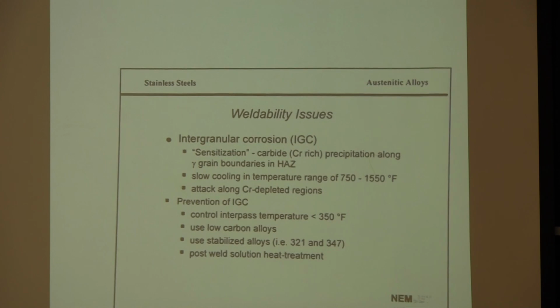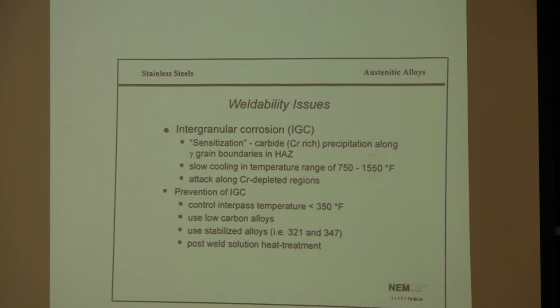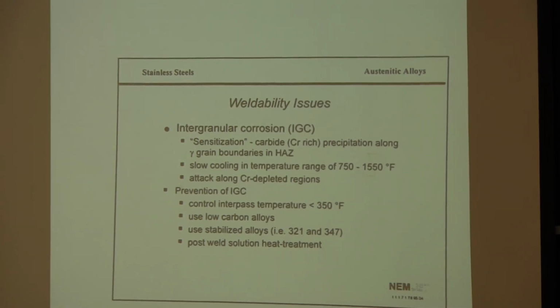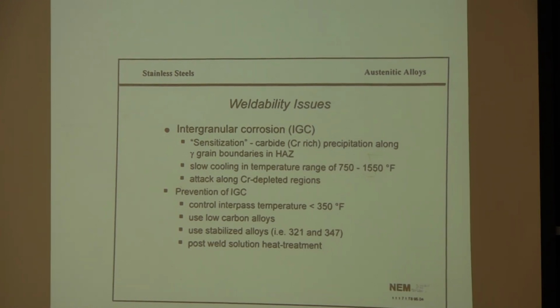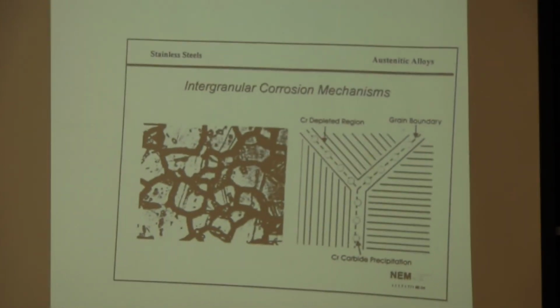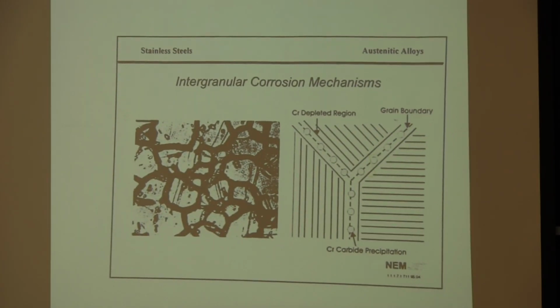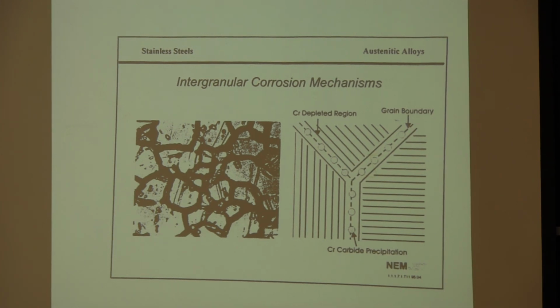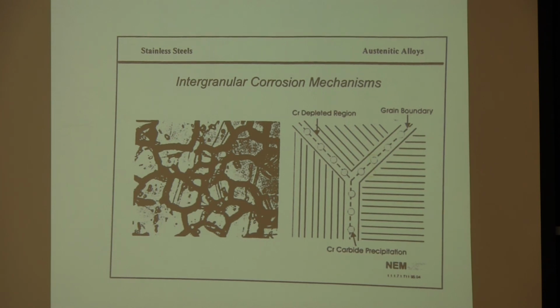There are other issues with welding of austenitic stainless steels, and one of them I wanted to talk about is intergranular corrosion, which occurs due to something called sensitization. And I think the easiest way to demonstrate that is with this picture here. Basically, when you weld on one of these types of stainless steels, you've got boundaries between the grains in your microstructure. And if you get this what's called intergranular corrosion, you get all these little corrosion ditches along the boundaries of the material. You can actually have complete grains that will just fall out of the material.